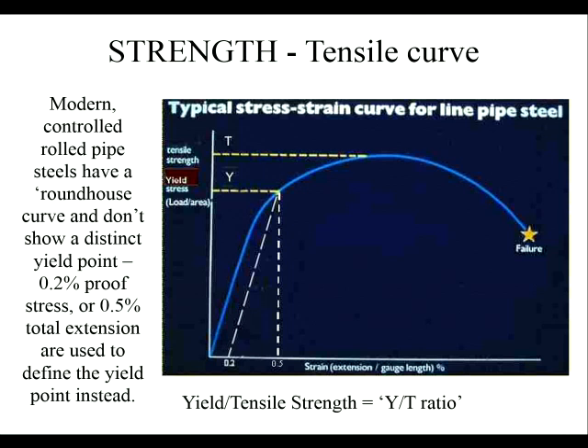So the stress strain curve of a modern controlled rolled steel, which is used in the manufacture, the steel composition might be exactly the same as in the previous case, but it's been prepared by the steel mill in a different way. It doesn't show that yield drop. The rolling process that is used will remove that serrated yield. And so there's a gradual transition from the elastic behaviour into the work hardening behaviour.